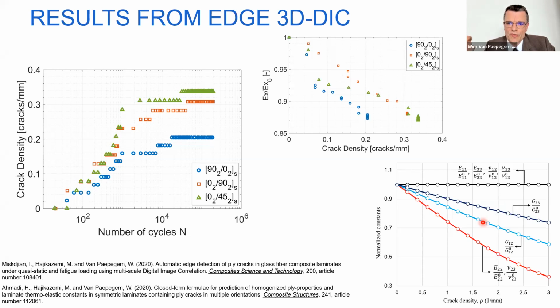You can also just freeze the damage state at a given moment in time, count the number of cracks. I have a certain crack density, I have a certain stiffness reduction for that crack density, and then check with your variational model if that crack density and that stiffness reduction match. And if the stiffness reduction is higher than the one that you get from your variational model, it means there are other damage mechanisms playing a role, like delamination, like fiber failure, which contribute additionally to the stiffness degradation.